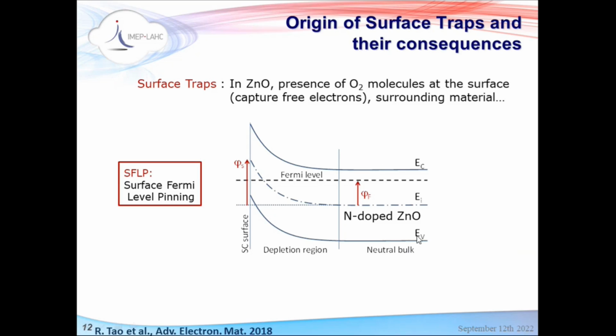I try to explain it with this energy band diagram. So because of this crystallinity that is different, it's because of the presence of oxygen molecules at the surface. This is in particular the case in zinc oxide. So you have these molecules at the surface and that will capture electrons. So basically what you have is a charged surface. So if it's charged, you will have a band bending near the surface of the semiconductor. And because of this band bending, you will deplete. There is a depletion zone, which means that there are no free carriers in this region. There is another effect that is the Fermi level that you can see here. It's changed compared to the bulk, and it's pinned to a different value. So this is what we call surface Fermi level pinning.